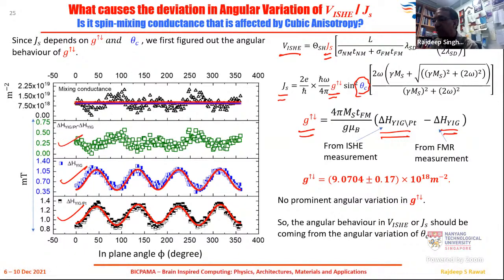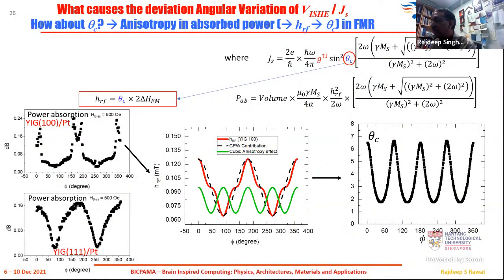So what we found is that the mixing conductance does have some variation. It seems to have some variation, but it is not very prominent. So we are not saying that it is totally gone or totally ignored, but it is not so prominent because the average of it is almost like a straight line. Now, the other factor that we need to explore is, what about theta c, the precession cone angle?